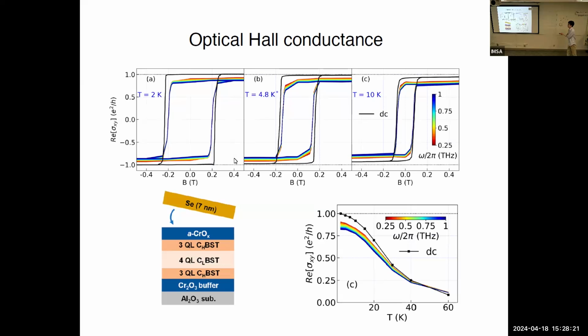And what we see immediately is that the response is close to quantization, but not exactly. You can see this, and also the coercive fields are slightly different. If I also look at this value as a function of temperature, we see that this hysteresis survives until about 60 Kelvin, similar to DC, but we still have this offset. So we started questioning why we wouldn't see this quantization in optical measurements, although we saw it in the case of bismuth selenide.